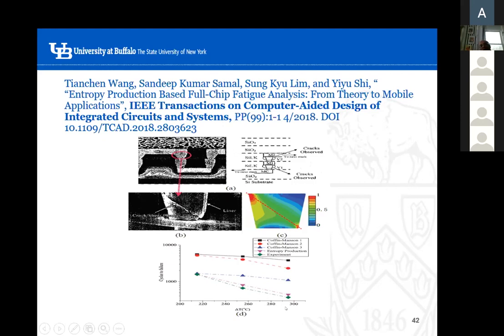And then of course, for different levels of delta T, fatigue life is going to be different. Fatigue life is smaller when the temperature is 300 degrees Celsius in the chip, because there is more differential expansion. The shear on the solder joint is bigger, and it will, of course, fail earlier.